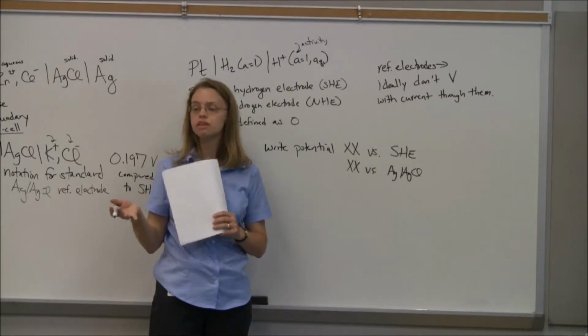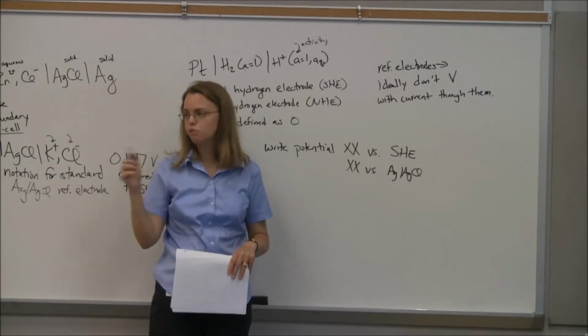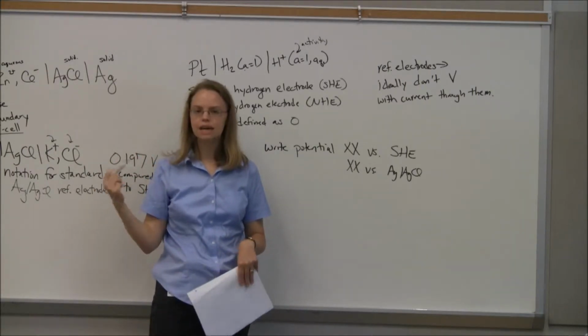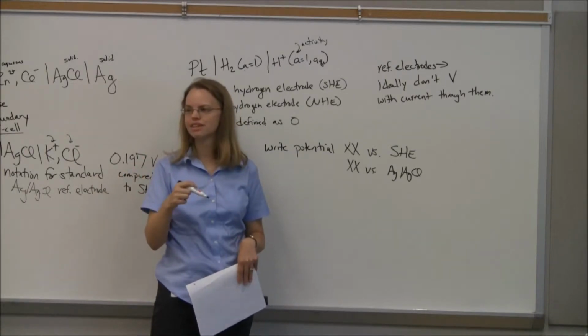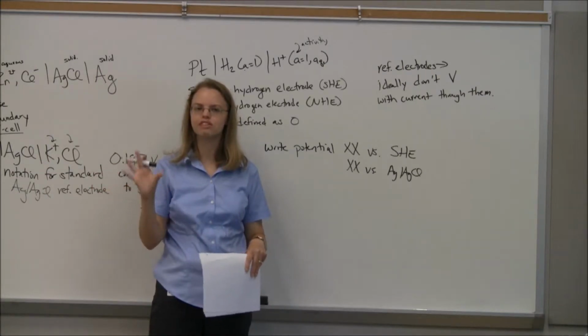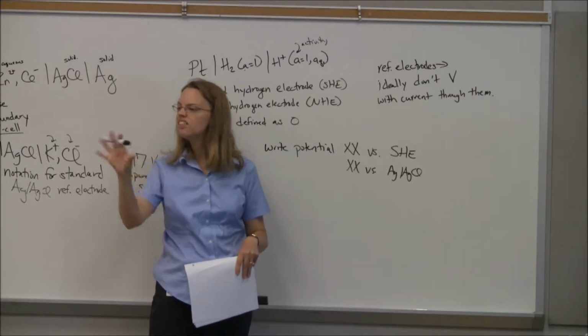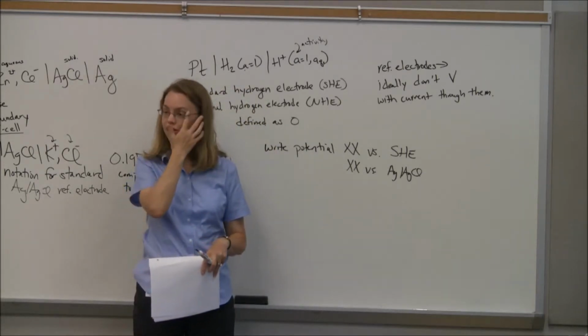All I did to believe this was to go to my electrochemistry book, look at the table of potentials in the back, and find what matched up for silver. That made sense. I believe it probably oxidizes. You get silver oxide. Now you're not measuring against silver chloride, you're measuring against silver oxide. The potential shift is about 0.2 volts. It would all work out just fine. They didn't prove that in that paper. I guess I should prove it. But they did show a way to get around it.